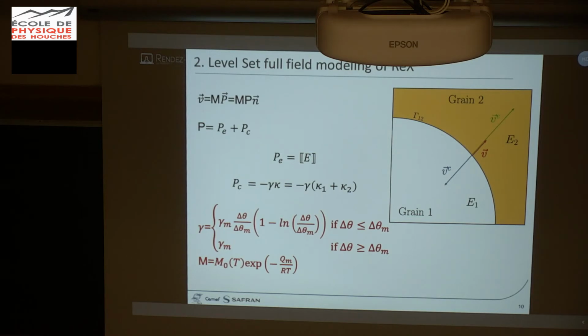of grain boundary migration. And finally, in level set simulation, all the physics is defined by this kinetic equation. The main aspect is to be able to precisely respect the driving pressure responsible for grain boundary migration. So, what you can find classically at polycrystalline scale is a monophase material. Here we don't have exactly a monophase material because I have detailed that we use second phase particles, but at the beginning of my presentation, second phase particles are considered as static. And finally, we can consider that we have only one phase which migrates during recrystallization, and we can say that we have this kind of monophase material for grain boundary migration.